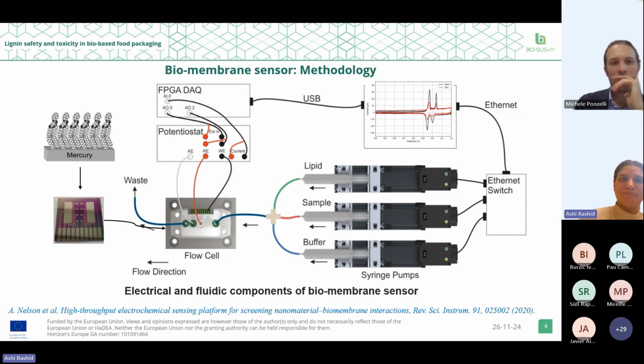From here, the potentiostat is used to apply a negatively increasing potential at a very high scan rate of 40 volts per second, using a technique called rapid cyclic voltammetry.